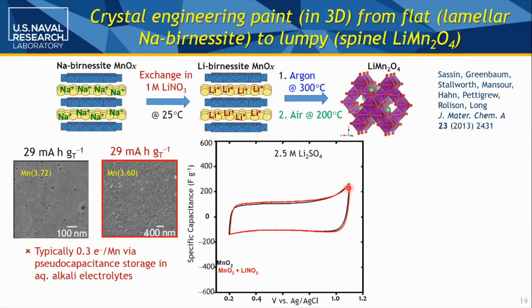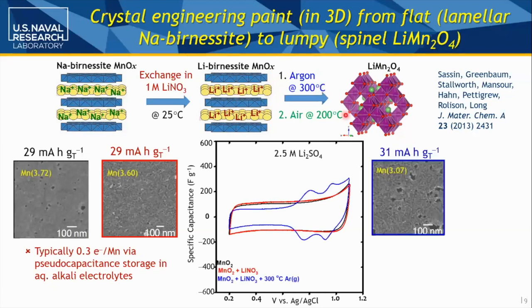But you can convert that layered manganese oxide form to something much more interesting, more like a battery material. So first they treated it in argon at 300 C. And you can see we're starting to roughen the surface a bit. We very much lowered the oxidation state closer to all of it being manganese 3. And you start to see things that pop up that look like a Faradaic response that you'd expect for something that's probably like an Mn2O3.